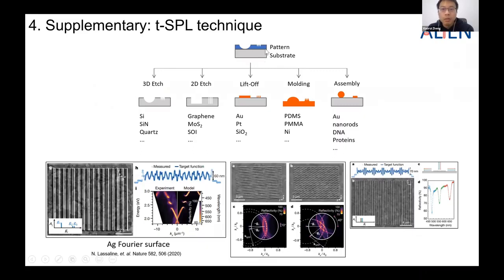I can give you an example here. So normally the process is we pattern structures in the PPA polymer here, and the structure will be further transferred into the silicon by either etching mechanisms here or by lift-off to create some additive structures here. And this year, a group used the NanoFrazor to pattern a Fourier surface in silver materials, and by only using the 3D pattern capability, they could achieve plasmonic resonances for a single unit, but at 3 resonance wavelengths. This is not possible without this 3D patterning capability here.